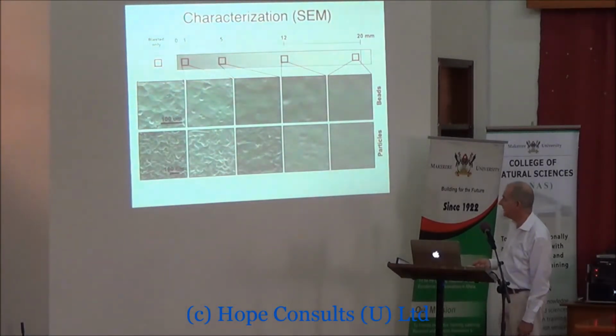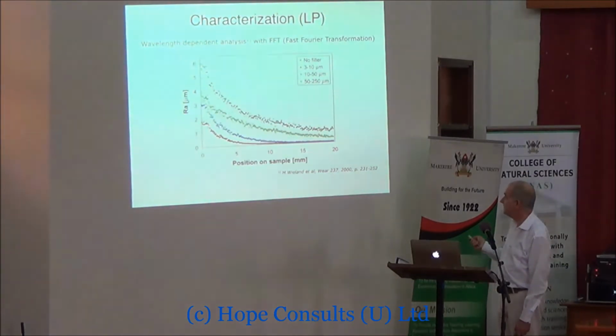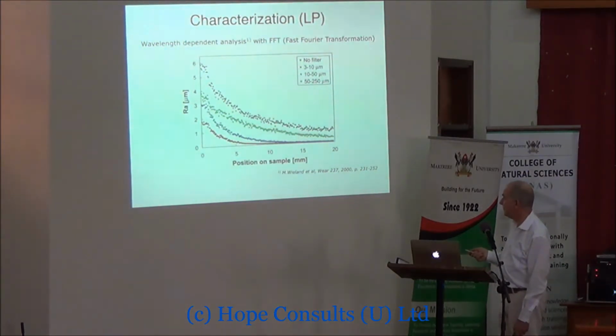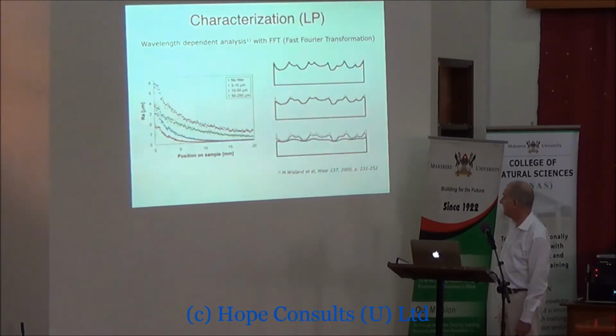And this is what it looks like under the electron microscope. This is the unpolished end, and this is the one that's been in the polishing solution long. So you can see the change in roughness here. And this is a measurement we did using laser profilometry, and you can see how the roughness is changing from one end of the sample to the other. And we filtered it at different wavelength windows, because different wavelengths affect the cells in different ways. So we actually Fourier transform the data and then look at the change in roughness with position. And this shows the way it gets polished.